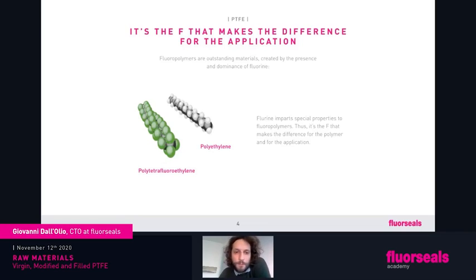We can see dark spheres, that's carbon, what we call the carbon backbone. It's the core of the molecule. And outside we have two different kinds of spheres, dots. One is green, the other one is white. Green dots are fluorine atoms, bigger atoms, as you can see from the drawing. Hydrogen atoms are smaller. As you can see on polyethylene, we still see the carbon. Carbon likes to do some bonding. And what does it mean?